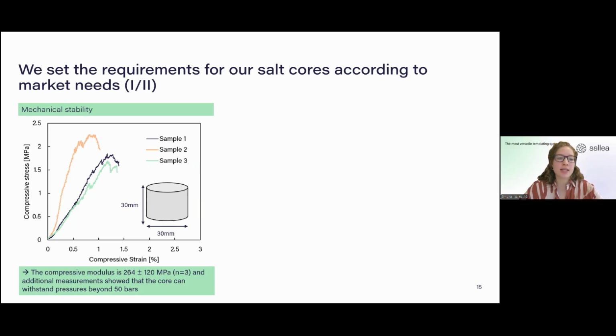And you can see that, of course, the material is a brittle material, and it has a compressive stress of around 2 megapascal. And we also took out the compressive modulus from these graphs, and it's roughly 264 megapascals. Of course, the standard deviation is a bit larger. As you can see, there is one sample that is a bit out of line compared to the others.